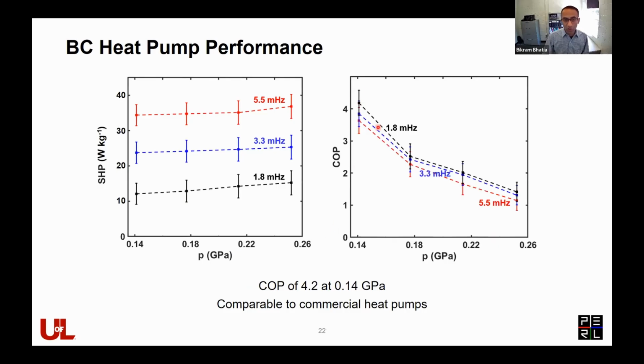And when you look at the COP, you see that as you apply higher and higher pressures, the COP actually decreases. That's again because we are in the regime where the denominator of the COP equation dominates, where the amount of work that you put in is dominant. As you go to higher pressures, even though the entropy change within the material increases, the work input term also substantially increases. So you have a decrease in the COP as you go to higher and higher pressure.